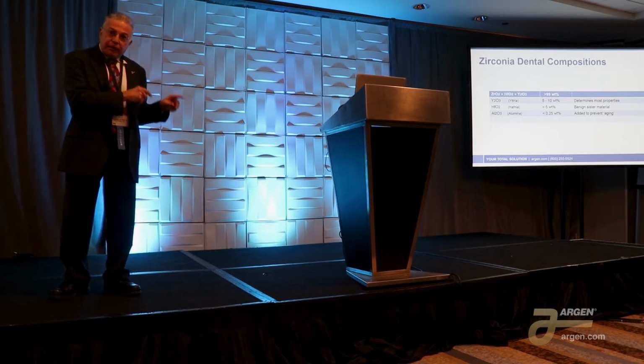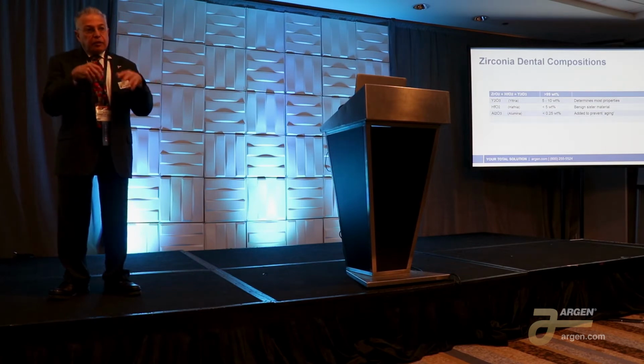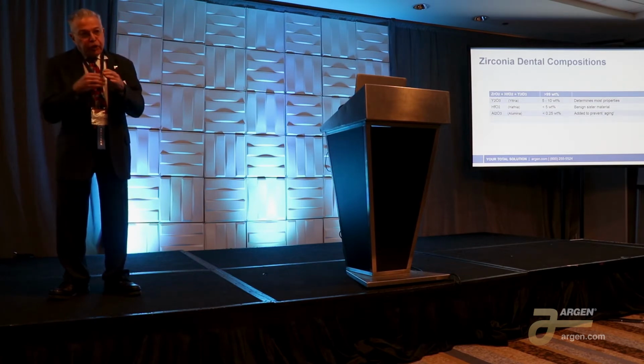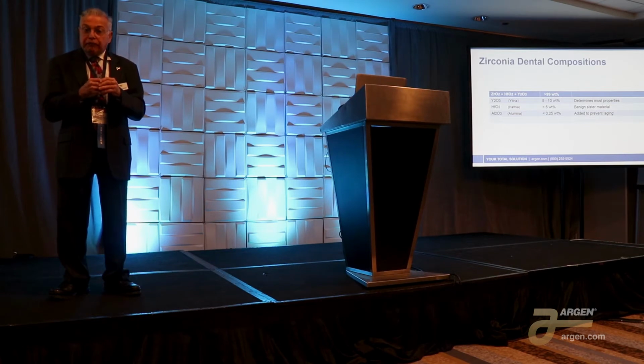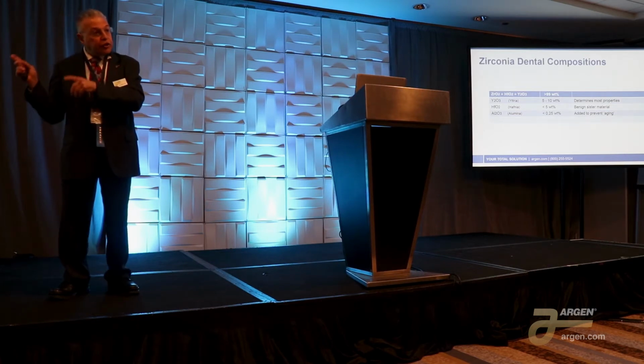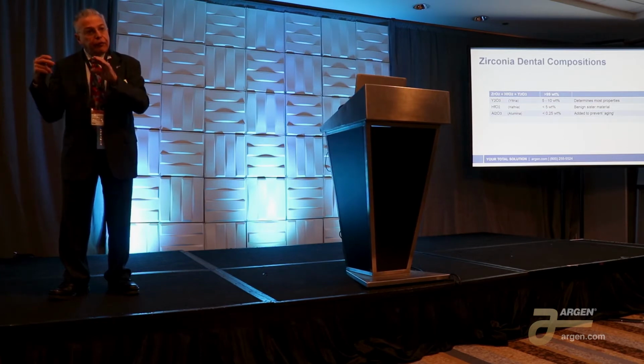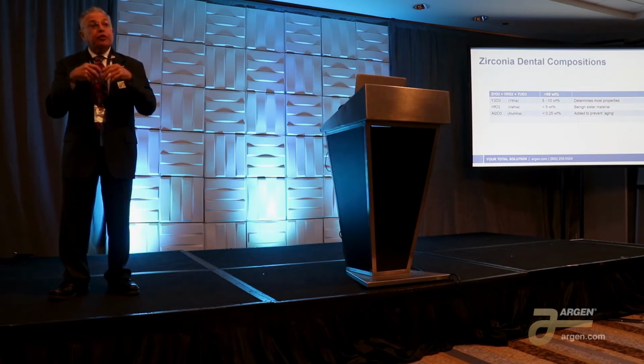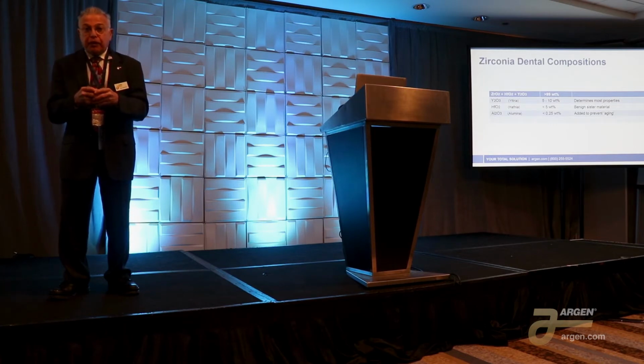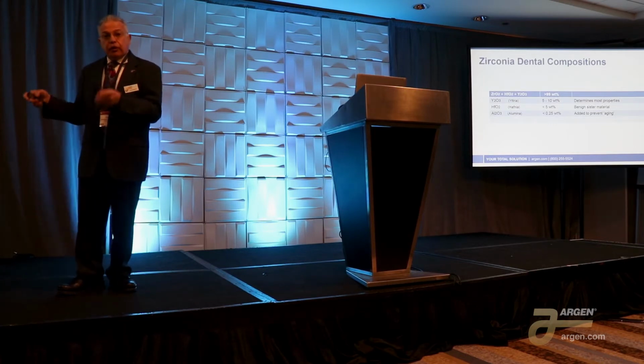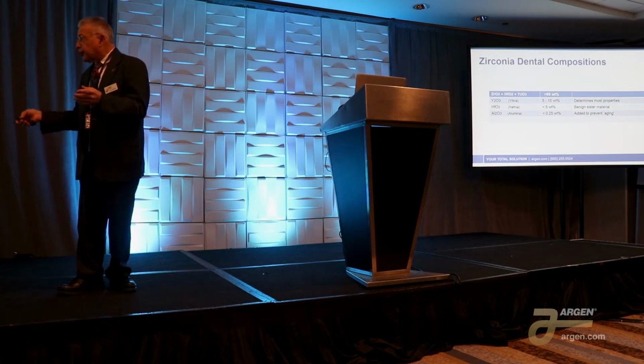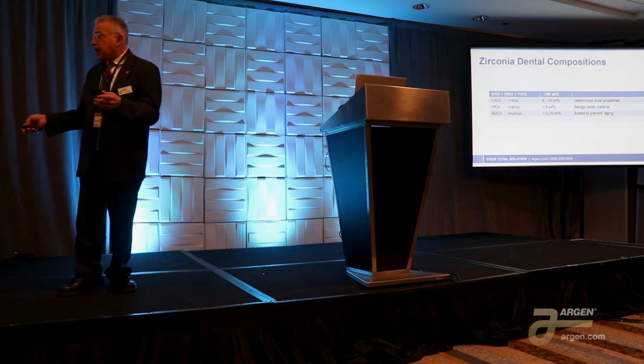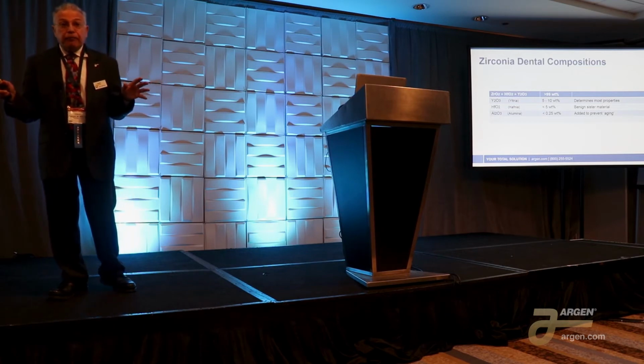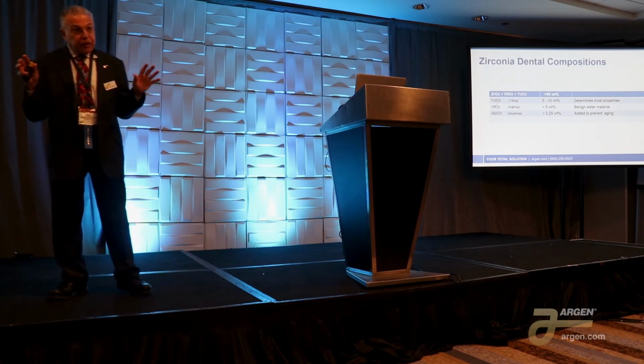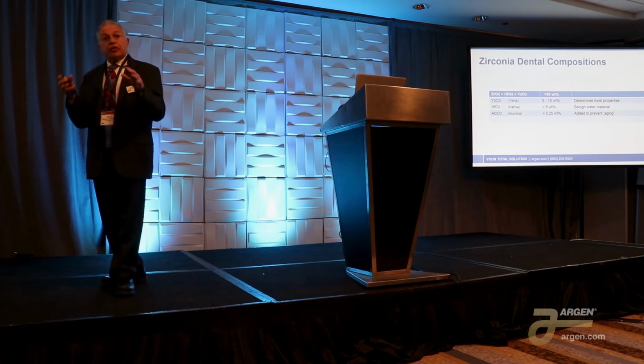What they found with the hip joints was that the body fluids, water, was getting pushed into the grain boundaries of the zirconia. Remember, I said zirconia is a crystalline ceramic. It has crystals, it has grain boundaries. You saw it on the picture. So water was getting forced into the grain boundaries and actually destroying the strength of the zirconia. By adding a little bit of alumina, and the first addition that they tried was actually 0.25%, they found they could eliminate that problem. So they left it at 0.25%. And that's what we started working with.